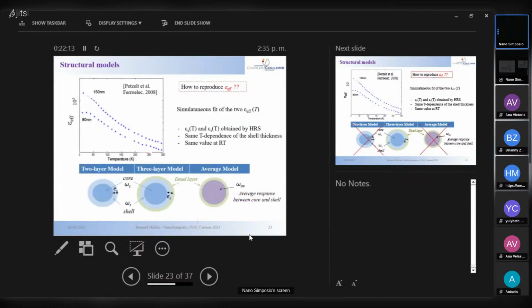Okay, so we have a lot of information. We have the volume of the core, we have the volume of the shell, we have the permittivity of the core, the permittivity of the shell, and now what we want is to reproduce the effective permittivity measured experimentally by electric measurements, this one. So we did a simultaneous fit of these two curves with the data we have, and we tried 3 models. The 2-layer models I showed you at the beginning, one average model here I will not discuss, and the third one.